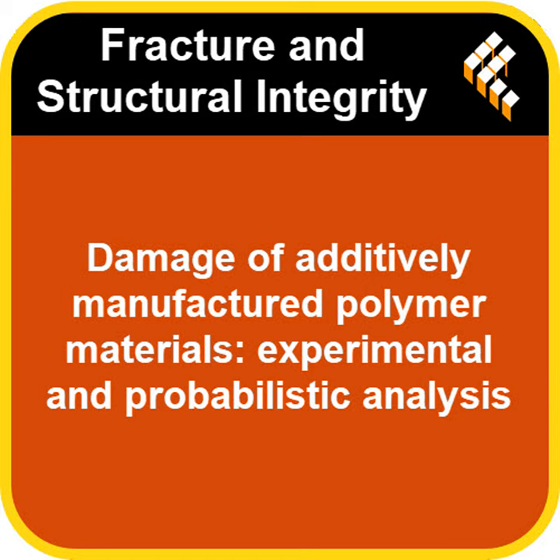Zone 2 is the stable plastic zone. This is where permanent deformation starts. The material stretches or deforms, and it stays that way even if you remove the load. So it's yielded. It's yielded, yes, but it can still carry weight. It's still stable. It hasn't failed yet. For the 90-degree, this might be around 35 to 40 MPa. Gotcha. And zone 3. And finally, zone 3 is the strength limit zone. This is where things get unstable. The deformation accelerates rapidly, uncontrollably, leading to abrupt, irreversible breakage. Failure. The end of the line. Pretty much. And for 90 degrees, that was anything above about 40 MPa.